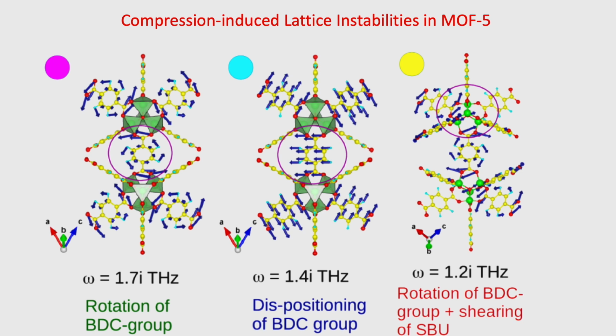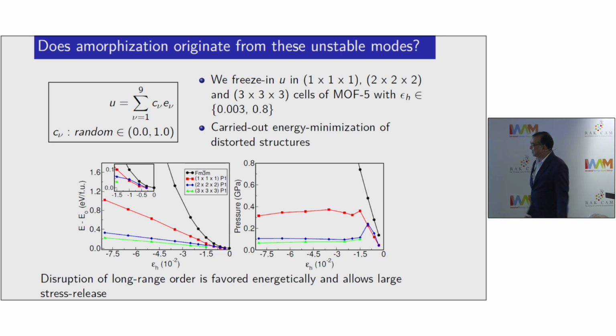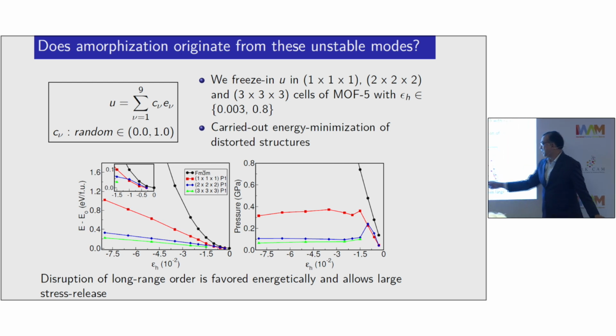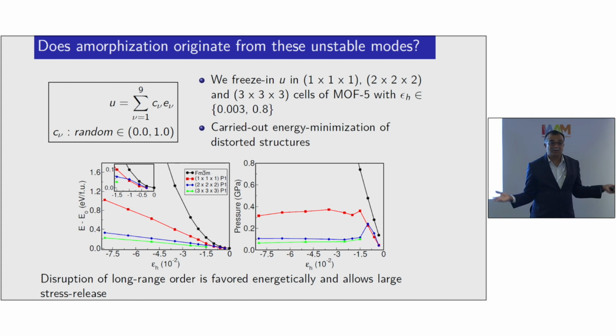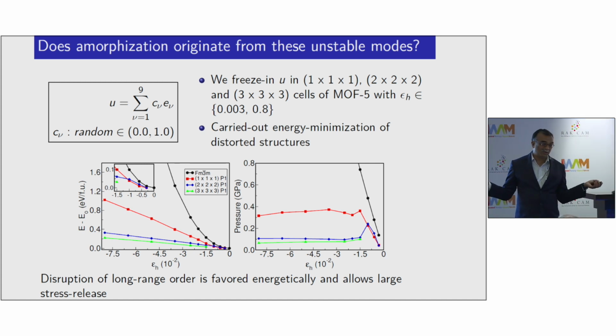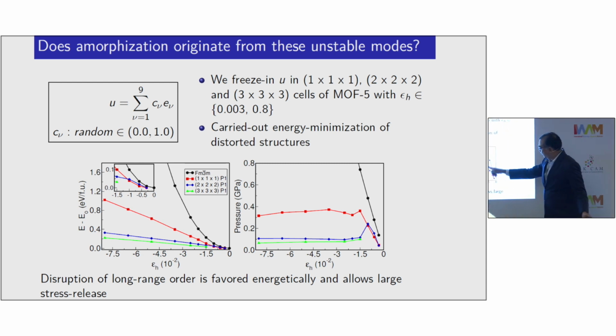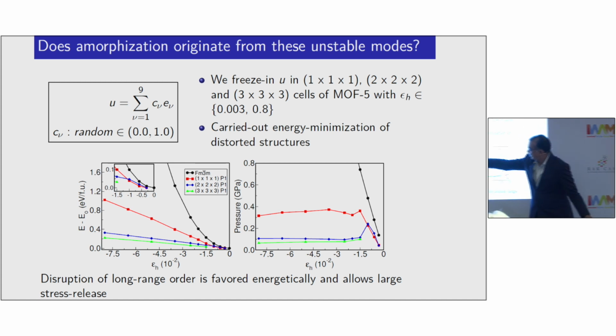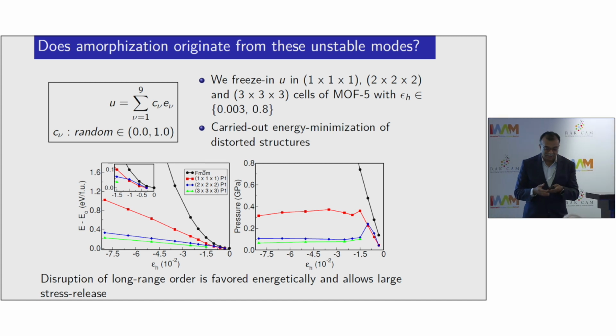This is the picture of these unstable modes. They involve rotation of the BDC group. Some of them involve displacement of the BDC group, and another is rotation plus shearing of the secondary building block units. All these processes are known to be something which can be destabilized very easily. And then you will see this is the picture which develops. If I don't allow the structure to disorder, the energy cost is very high. This is the pressure versus strain curve. And the moment you allow the disorder to come in, associated with these unstable phonons or distortions or disordered structure, the stress is released very rapidly at fairly small strains, and you see the pressure drops significantly as well. And that is the reason why MOF5 amorphizes at unusually low pressures.